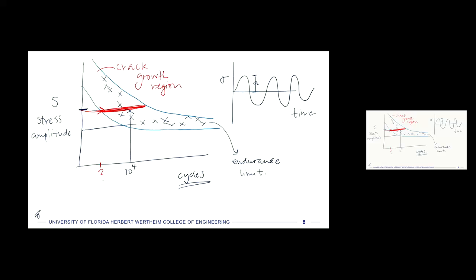So these types of SN plots are all for high cycle fatigue. And we say that high cycle fatigue is greater than about 10 to the 4th cycles. On your SN plots, you may go back to 10 to the 3rd, just for a reference point. But if something fails at less than 1,000 cycles, or maybe even up to 10,000 cycles, that's low cycle fatigue. If it fails at greater than 10 to the 4, and then up to 10 to the 6 in some cases, or 10 to the 9th in other cases, depending on the conventions that you're thinking about, those numbers of cycles, so 1 million or 1 billion, are considered infinite life. The stresses are low enough where we don't expect any cracks to initiate. So that's the general approach to thinking about fatigue.